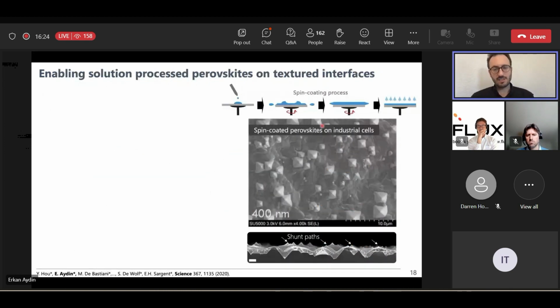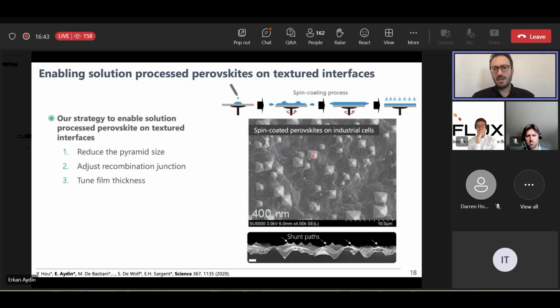And this was also the case when we attempted for the first time to spin coat the perovskite on top of commercial grade crystalline silicon wafers. The very first thing that we found was that the pyramids were actually coming out, and basically this device is by default shunted. So we overcame this issue by following a few-step strategy.